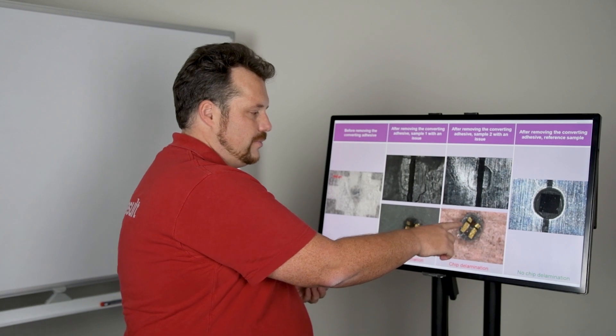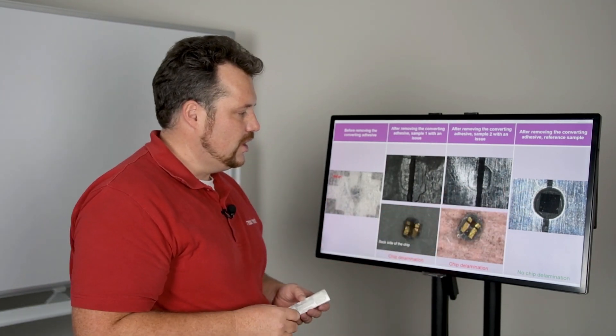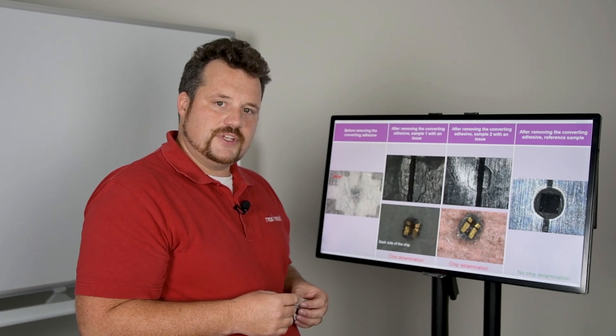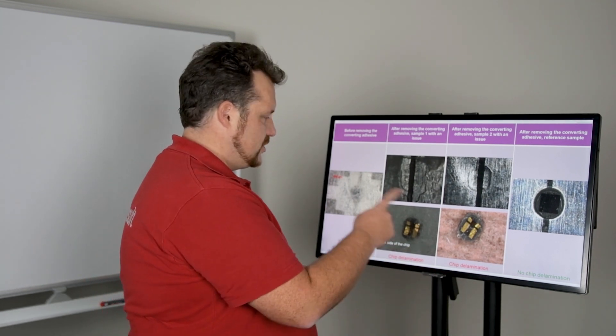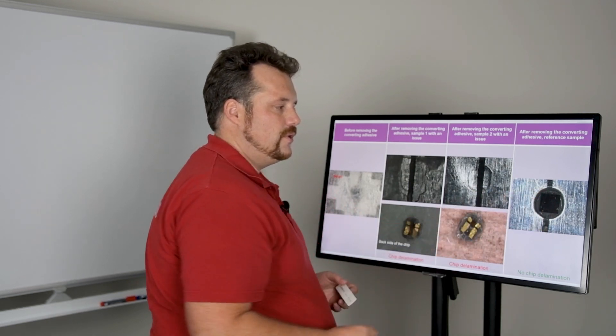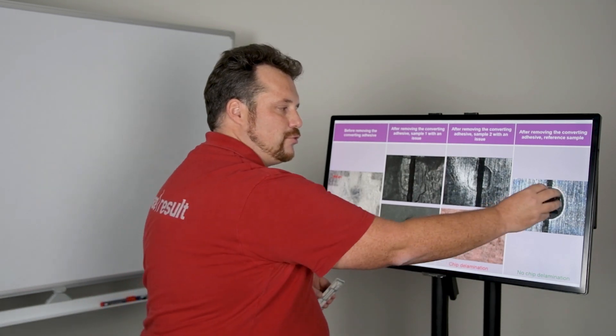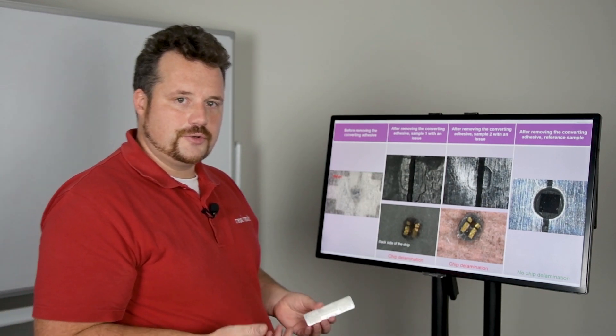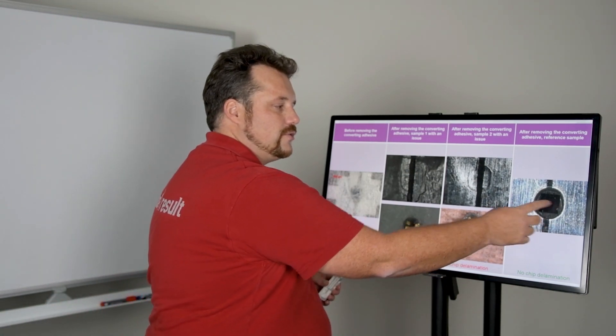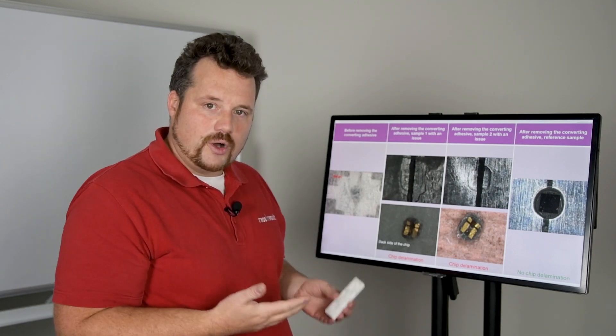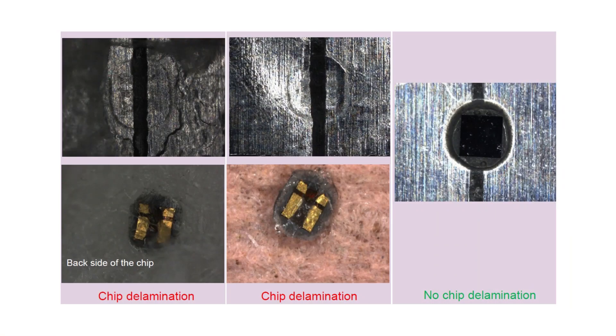This is the backside of that chip where you can see electrical contact fields called bumps, and those connect to the aluminum antenna via a conductive adhesive. In the process of manufacturing, this chip is what we call bonding—is bonded to the aluminum antenna by pressure and heat on that adhesive, which cures the adhesive, generates an electrical connection to the antenna and holds the chip in place. Obviously this is not our process, but as this is our chip and we have very close connections to the people doing this for us, we have very good insights of what's going on there.